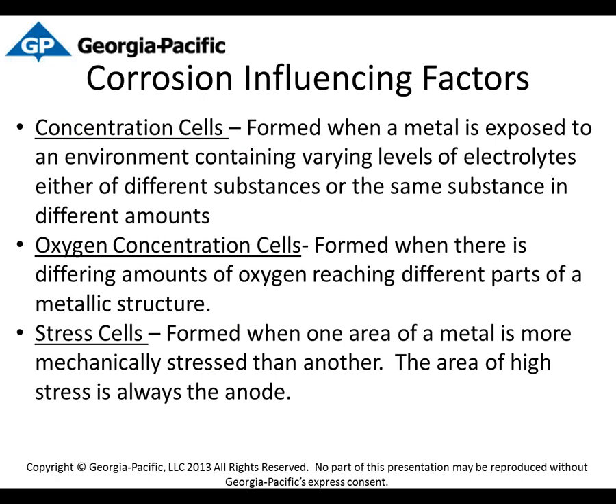And stress cells, formed when one area of metal is more mechanically stressed than another. The area of high stress is always the anode. And the reason I picked out these three influencing factors is because these are commonly seen with MIC, microbial influence corrosion. A lot of stress cells can be on welds or welded joints if they're not properly stress relieved. But more importantly, on oxygen concentration cells and concentration cells, the bacteria can actually form these types of cells on the metal surface.